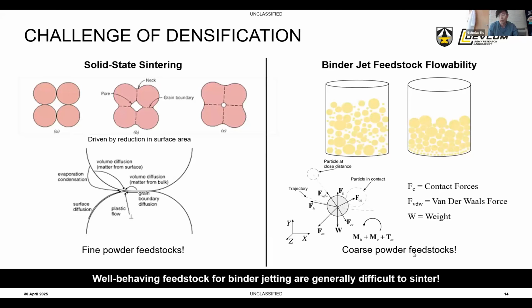90% of the time when we're doing ceramics research, we concentrate on solid state sintering to densify these materials. And that's a surface area driven effect, right? So we want extremely fine powder feedstocks to allow for solid state sintering. So generally, well-behaving feedstocks for binder jetting, for actual printing, for forming, are very difficult to sinter. So that silicon carbide AFC logo on the previous slide, we were able to print that, but the particle size was so large it would not sinter.